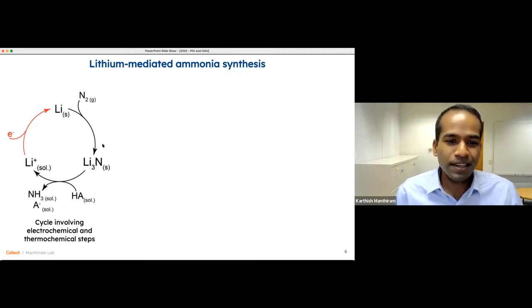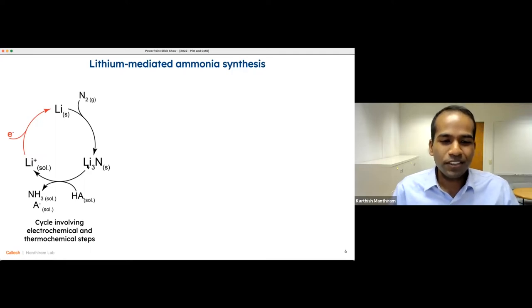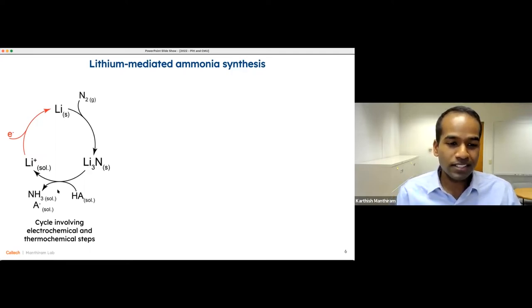So one ends up making lithium nitride. That lithium nitride can then be protolyzed, so we can react it with a proton donor in solution, which we'll leave generic for the moment. That in turn leads to exchange of the lithium ions with protons, making ammonia, and discharge of a lithium ion into solution, which can then be plated to make lithium metal. So one can then continue around this cycle.